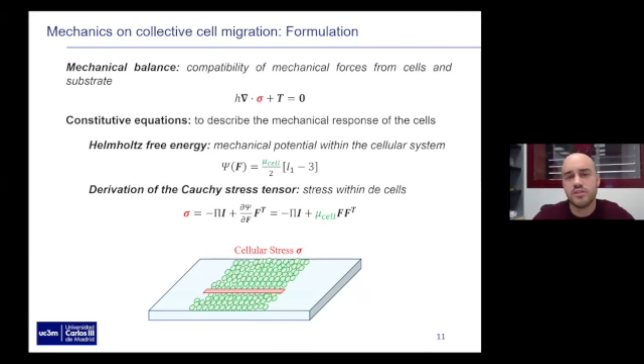So once we have defined that, we need to define what is happening inside the cellular stress, right? So basically, we said, okay, let's use some hyperelastic theory. The main idea here is that instead of defining directly the constitutive relation, we're going to define a mechanical potential. So basically, this is the mechanical energy that is stored in the system and we can recover at some point. Using some solid mechanics and thermodynamic principles, we can reach the following consistent relationship between the deformation state of the cellular system, defined by F, the deformation gradient, and our Cauchy stress tensor, our true stress. And then we can observe that we have two components, with the first one being a volumetric one, with P being the pressure that we are going to get from boundary conditions and some consistency equations. And then we have a second term related to the shear, where mu cell is the stiffness of the cellular system, basically the shear modulus.